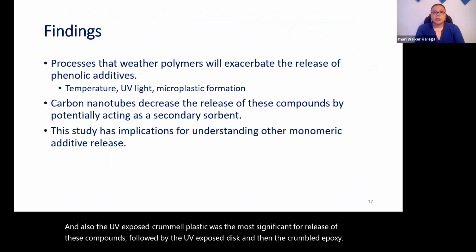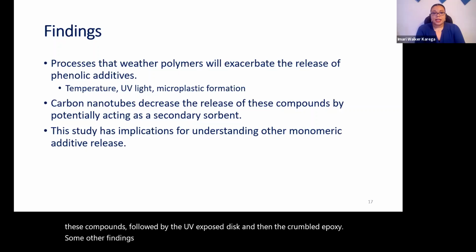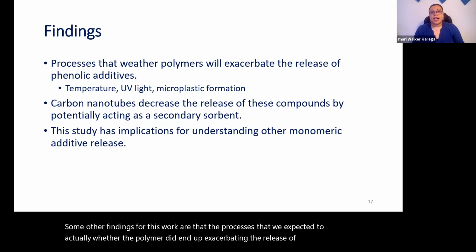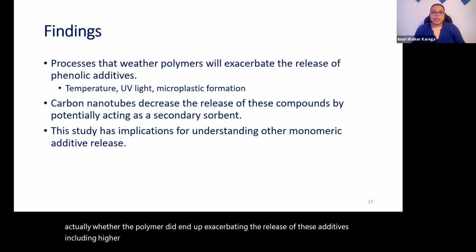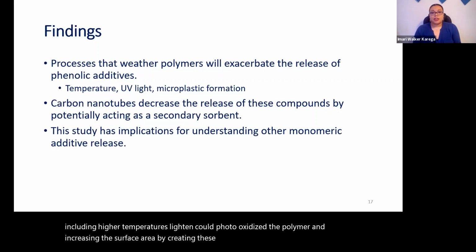So some of the findings for this work are that the processes we expected to actually weather the polymer did end up exacerbating the release of these additives, including higher temperatures, UV light that could photooxidize the polymer, and increasing the surface area by creating these microplastics increased the release of both tert-butylphenol and bisphenol A.